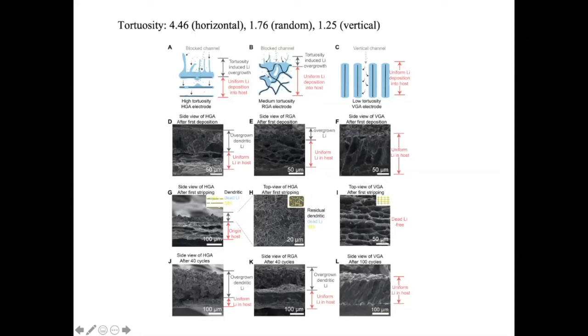I want you to focus on the bottom SEM. This is a cross-section view after 40 cycles for the horizontally and randomly aligned. You see this is highly porous, looks like more mossy lithium formation. But the vertically aligned one, even after 100 cycles, is a very solid, very dense film, and lithium metal deposition goes inside very nicely. So a very clear difference in the behavior.